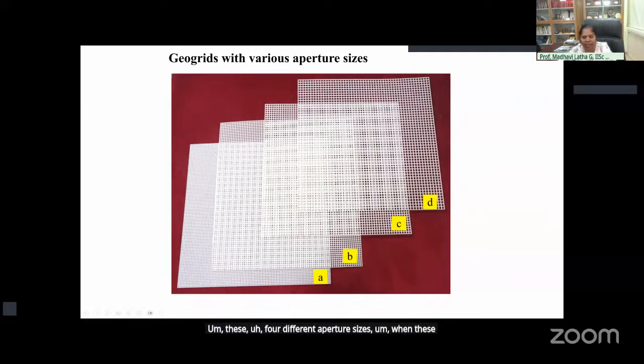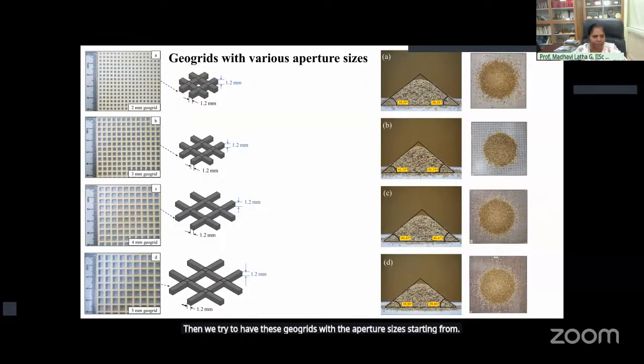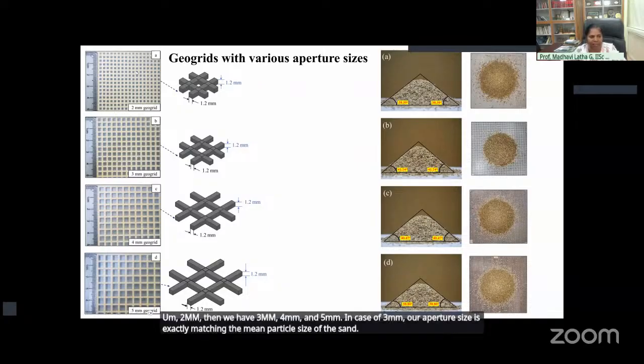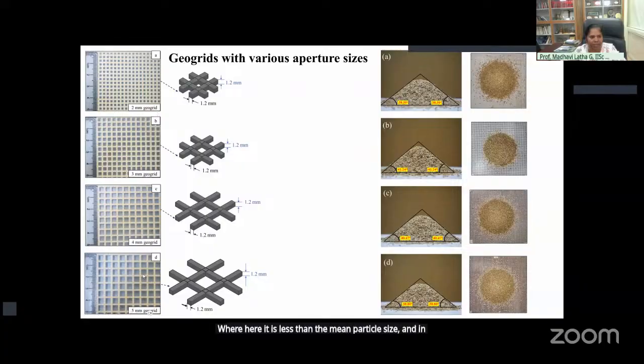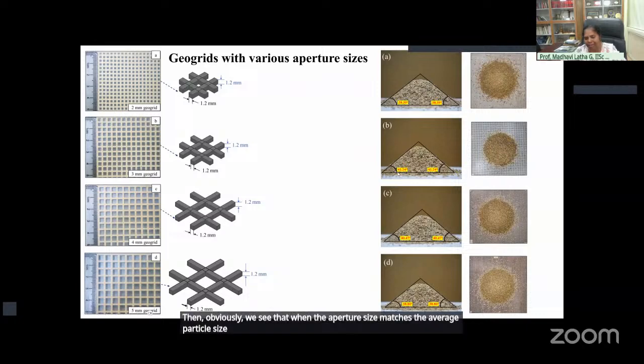When these geogrids are interacting with sand, with an average particle size of about 3 mm, we try geogrids with aperture sizes starting from 2 mm, then 3 mm, 4 mm, and 5 mm. In the case of 3 mm, our aperture size is exactly matching the mean particle size of the sand, where here it is less than the mean particle size, and in the other 2 cases, the aperture size is bigger. Then when we do the angle of repose test to calculate the rough residual friction angle, obviously we see that when the aperture size matches the average particle size, we have the maximum residual friction angle, which is about 41 degrees. In other cases, it is slightly lower.